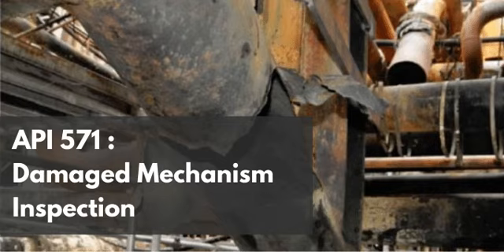Laboratory methods. Yeah. The text explains that the absolute most effective method of detecting or confirming 885 degrees Fahrenheit embrittlement involves physical destruction of the component. Destruction. Yes. You have to physically cut out and remove a sample of the suspect material from the actual equipment. You literally have to cut a boat sample or a coupon out of your live pressure vessel or piping system. Yes. You take the equipment out of service, you cut a piece out, and you send it to a metallurgical lab. Whoa. And once that sample is removed, it must be subjected to specific mechanical tests.